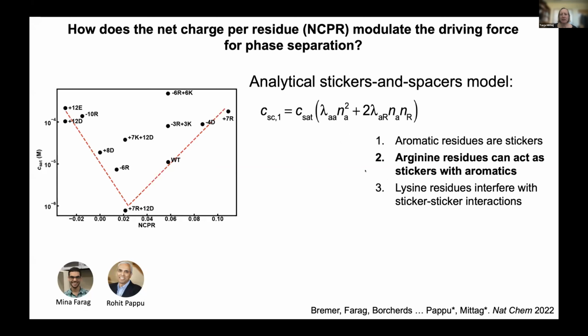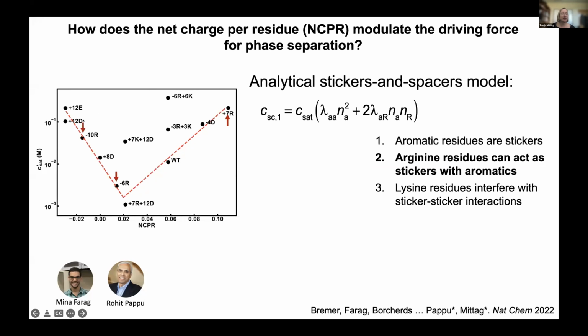We said, okay, so if we have, in addition to aromatic residues as stickers, if arginine residues can also act as stickers, and we haven't taken that into account in our data or in the selection of our variants, then we can rescale the experimental saturation concentrations to take this into account, that our arginine residues can make interactions with aromatic residues. And when we did this and rescaled the experimental values, indeed, these data points for arginine variants are nicely moved onto this V-shaped plot.